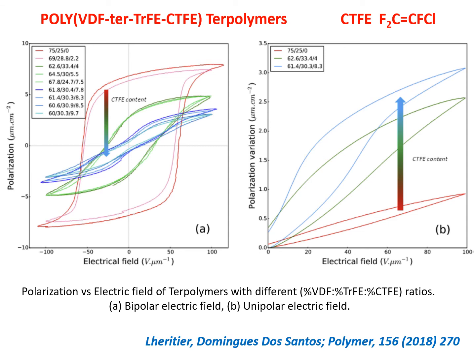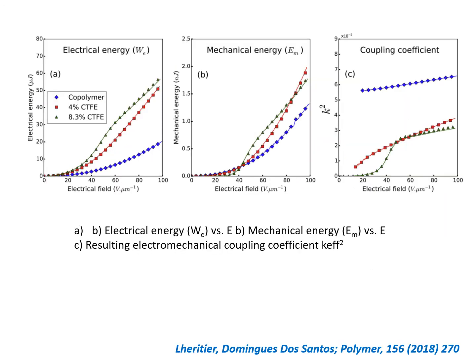The curve regarding the content of CTFE shows that the higher the content of CTFE, the slimmer the hysteresis, showing that you go to a piezoelectric system here. This paper also corresponds to the investigation of electrical energy versus electrical field. As you increase the content of CTFE, you increase the electrical energy, here 0, 4, or 8. And this is the same for the mechanical energy. Also the k2, which represents a kind of electromechanical coupling coefficient, shows lower values compared to the copolymer.